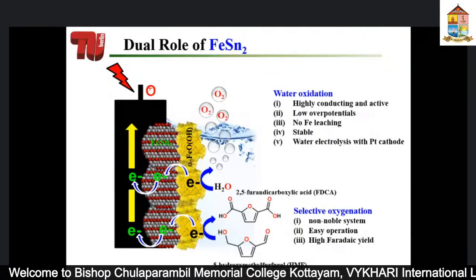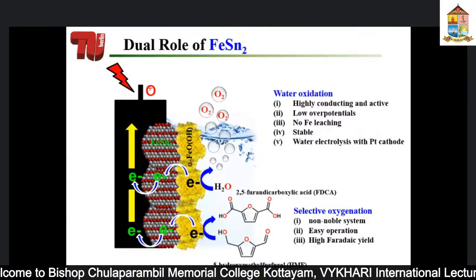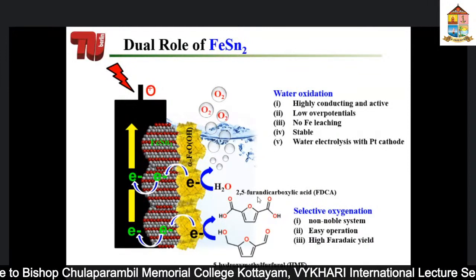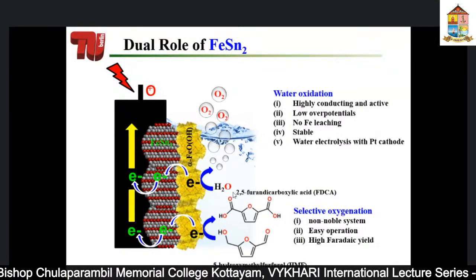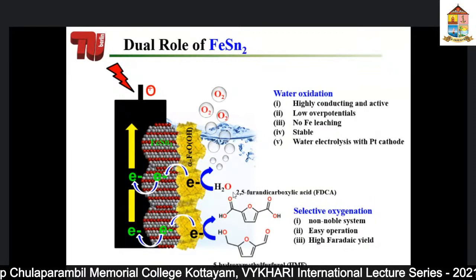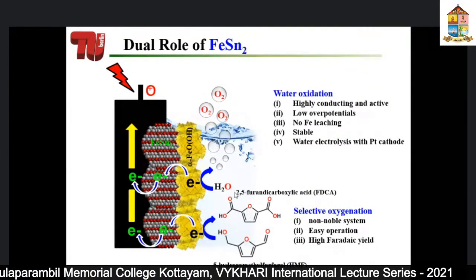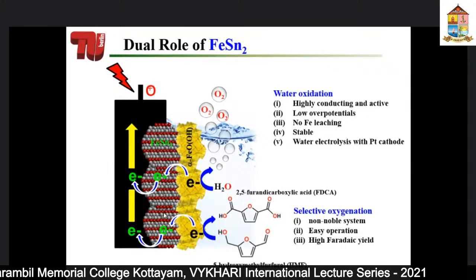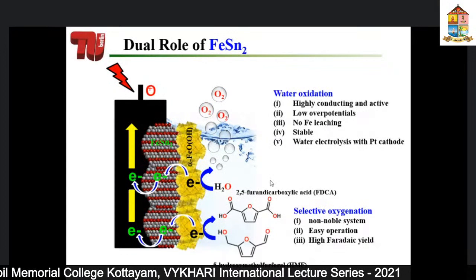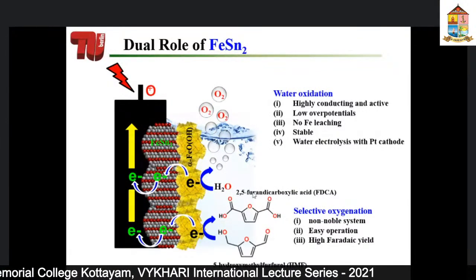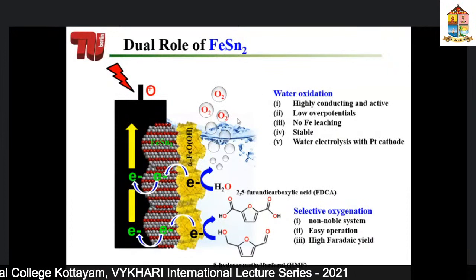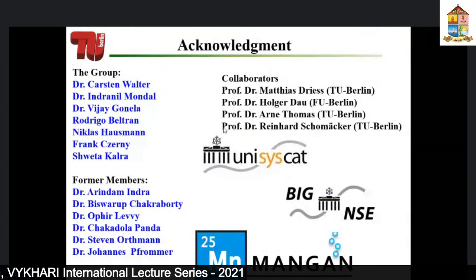HMF, we call it. So 5-hydroxymethyl furfural, which is a good precursor to form FDCA, 2,5-furan dicarboxylic acid, which is an important precursor for the polymer industries. So by using one particular catalyst, you can change the structure, and you can use it for two different reactions, which are highly challenging reactions, as I already told you. This reaction is very demanding compared to hydrogen evolution, because this reaction determines how the efficiency of hydrogen could rise.